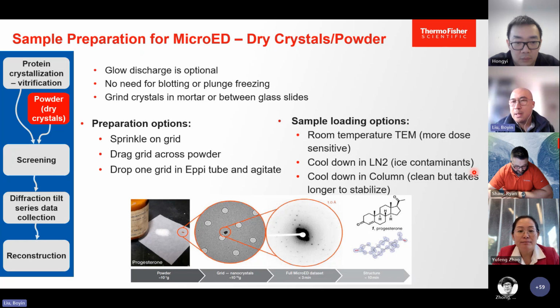You're going to have to spend lots of time screening. Or you can also choose to cool down in the column. Just load the samples at room temperature and let the sample cool down in the column, but it takes a very long time to stabilize. But the sample will be cleaner.